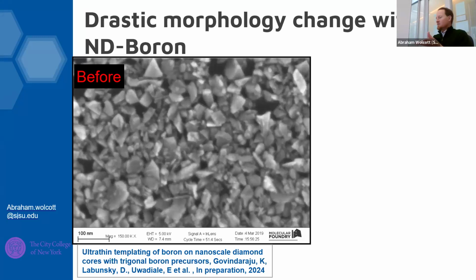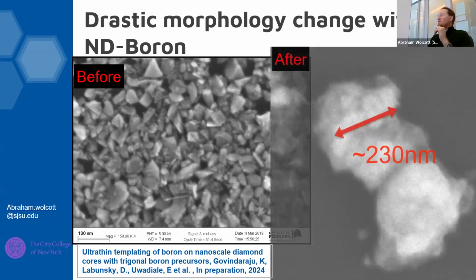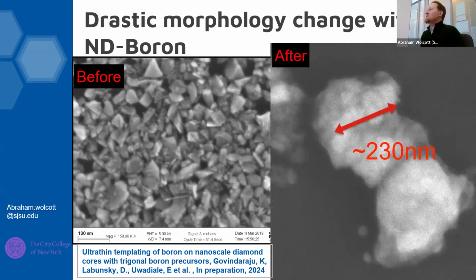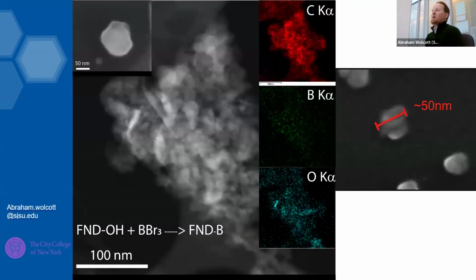Many of you have seen similar types of SEM images. We then do our chemistry and we end up with this odd stuff. We have this layering, we can barely see what's going on. Why is it diffuse? Why does it look like the diamond has become rounded? We can end up picking out single nanoparticles, and we can see those on the left-hand side, where we can see like a 50 nanometer particle, again, very diffuse.